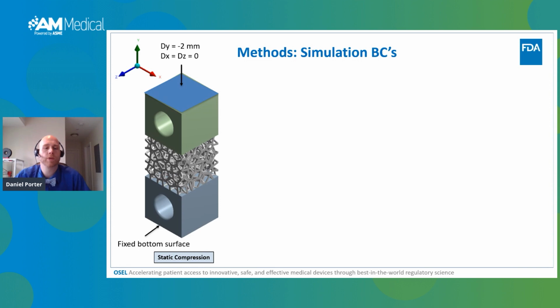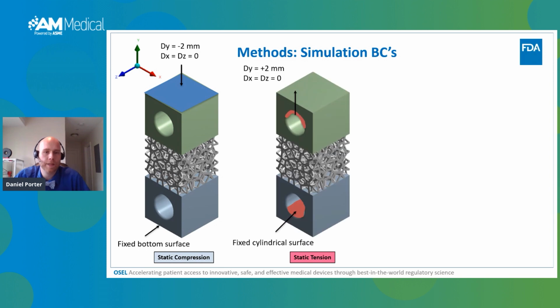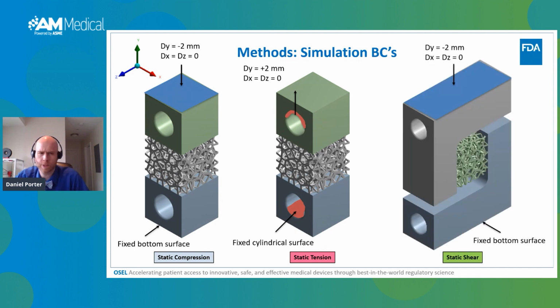So FEAs have boundary conditions, and so let's talk about those. For the compression samples, we completely fixed the bottom surface, and on the top we applied a 2 millimeter displacement. We restrained the planar movement on the top face. The tension samples were nearly the same, except we fixed a cylindrical surface on the bottom and applied a displacement to the cylindrical surface on the top. And the shear samples were similar to the compression samples, constraining the planar movement on top. Later on, I will discuss why we think that assumption was reasonable when I show you some images of the experiments. So I'll go into that at that time.